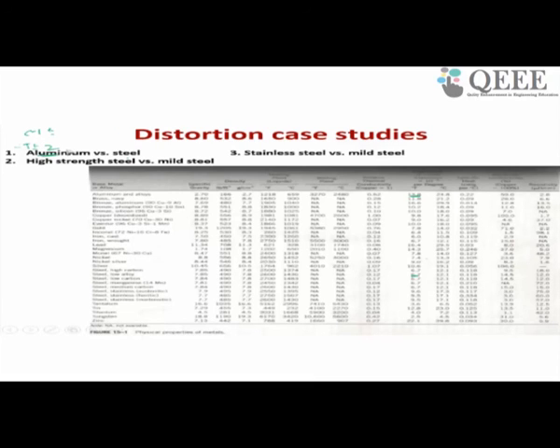Aluminum, then what about thermal conductivity? Thermal conductivity of aluminum is again 2 times higher. So residual stress will be less. So from a thermal conductivity point of view, aluminum will have less residual stress. However, from a coefficient of thermal expansion point of view, aluminum will have high residual stress. Sorry, high distortion. Okay.